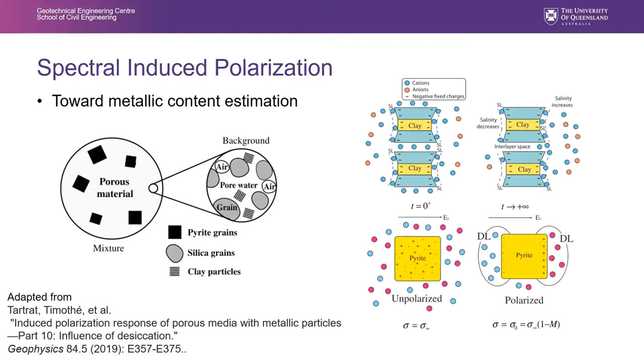So if we talk about tailings, there is a lot of interest in using this low frequency method called spectral induced polarization. If we consider a soil with pyrite grains and with clays and solid particles, there is a very big difference in the electrical double layers. The clays will create a very specific electrical double layer, and a grain of metallic particles will create a very different diffuse layer structure. So this is very typical. And this process is going to be linked to the size. So depending on the size, you might reach different processes and different relaxations in different frequency ranges. And this was used by some authors.